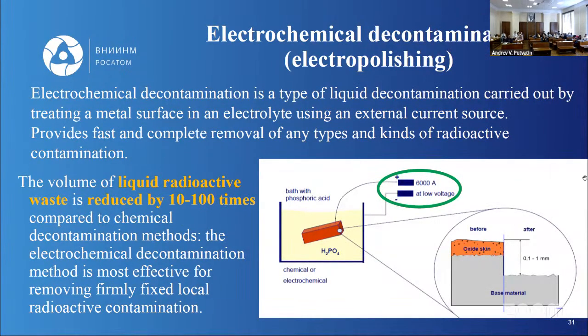Also, we can apply activation of chemical reagents. It is the application of electrochemical decontamination, or electropolishing, the other name of this process. Electrochemical decontamination applies electrical potential to this media, and we can apply low voltage and high electrical power in a water solution of, for example, phosphoric acid. Then, with the application of current on the surface, we can remove not only chemical oxide layers, but also a thin layer of metal from the surface.